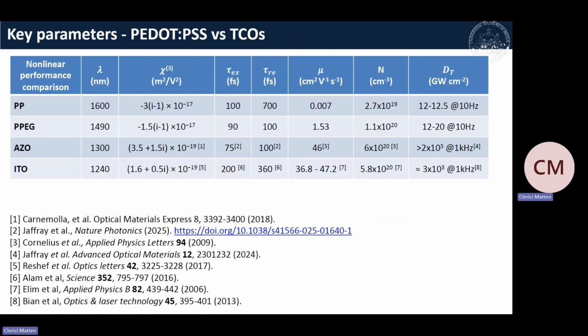Because at the very beginning we wanted to compare it with TCOs, we tried to sum up everything together. And what we found is that the nonlinearity of those organic compounds is actually 2 orders of magnitude bigger. The time scale of the response is similar. I want to say that it's probably limited by our detection system or our pulse duration in this case. The mobility of the organic compounds is smaller, and the damage threshold is actually much lower. So on one side, we gain 2 orders of magnitude. On the other side, of course, we lose because organic compounds tend to break more easily. But it's still a very good nonlinear platform.